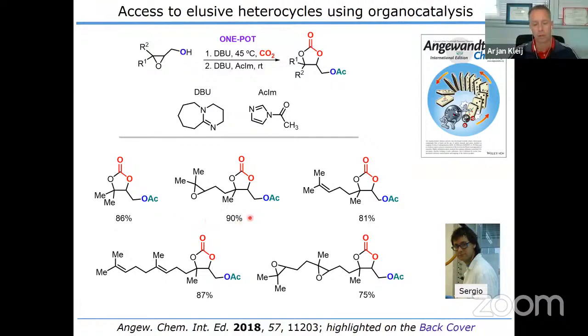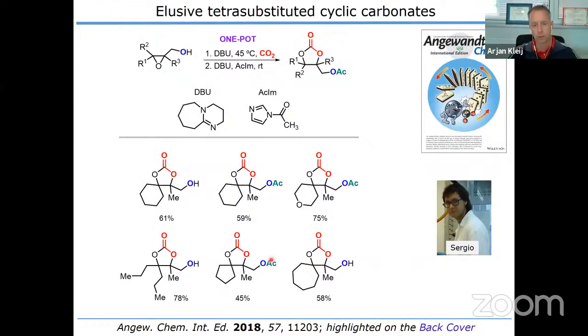And you can get good yields of these, what I would call rather elusive structures, where we can have different functionalities present in the cyclic carbonate target molecule. So double bonds or epoxides or even two double bonds or epoxy groups. So Sergio took that one step further in order to make tetrasubstituted carbonates. At that time, I think we take into account CO2 epoxide coupling reactions was the first example of a more general process that allows you to do that, especially under organocatalytic control. And here you can see that we have produced a number of interesting and rather elusive type of cyclic carbonates.